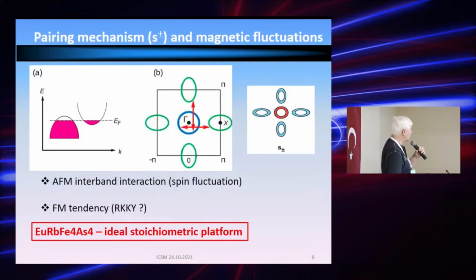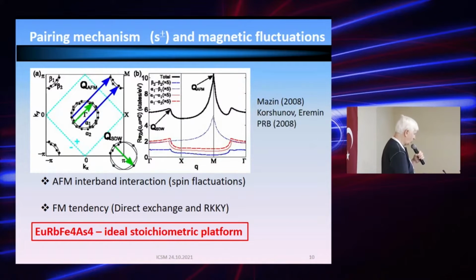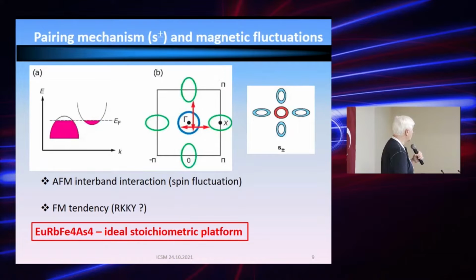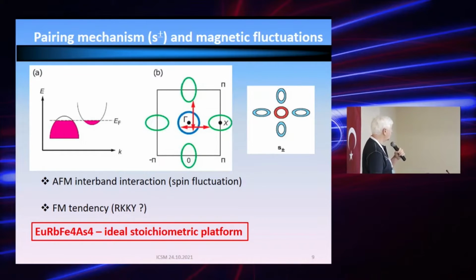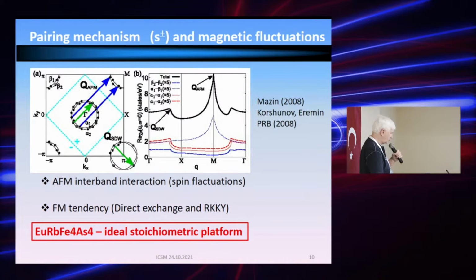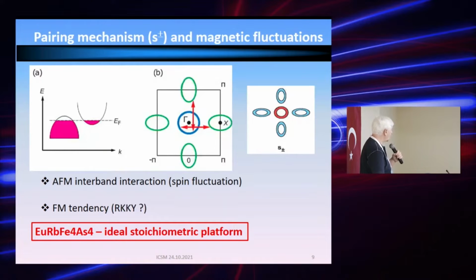To remind you the appearance of superconducting pairing, I show the old picture suggested by Igor Mazin and by other people like Korshunov. So basically, in all these materials of the 122 class of iron arsenide, there are electron and hole bands which form several, for simplicity, cylinders along the gamma point and along the X or M points of the Brillouin zone.